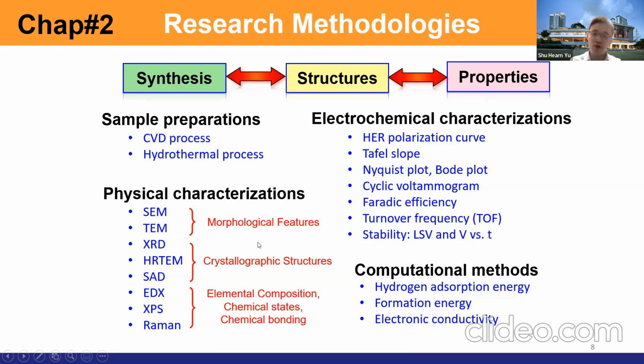So we try to build a relationship between the structures and the performance. So it's a structure-property relation, we try to correlate the relationship. After that, we will seek our collaborators to do some computational methods to carry out some insights. For example, we will measure the hydrogen adsorption energy, usually the delta G. The closer to 0, the better. And then the formation energy and electronic conductivity.